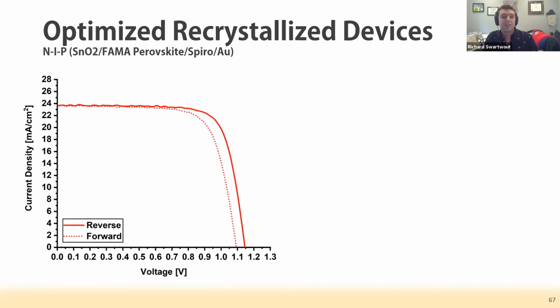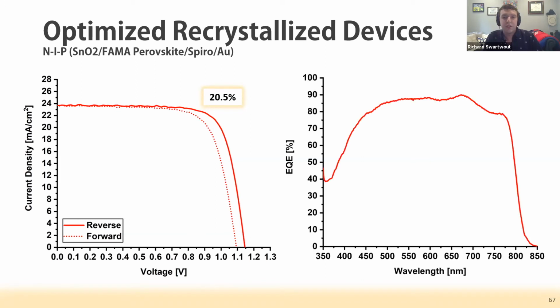Our champion device today is scanned at 20.5% with a stabilized power output of about 19. EQE shows above 90% in generally the 450 to 750 nanometer regime. Both these things really reinforce that this is a method that not only can provide high efficiency devices, but can easily scale between small and large.